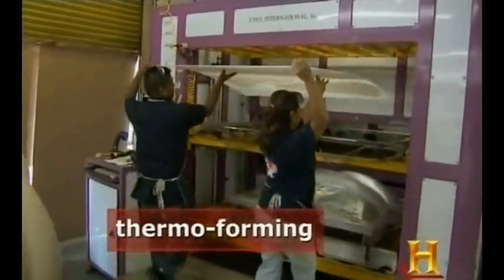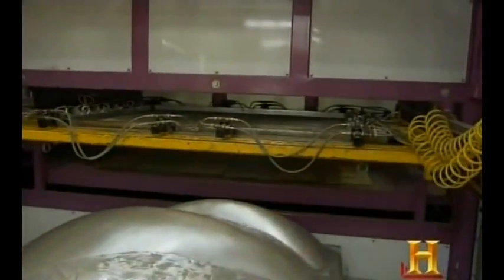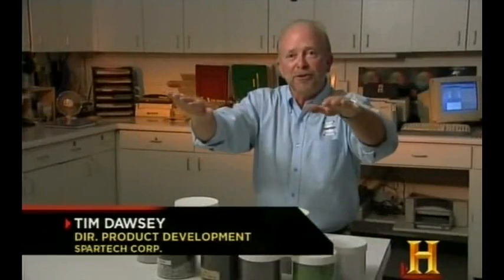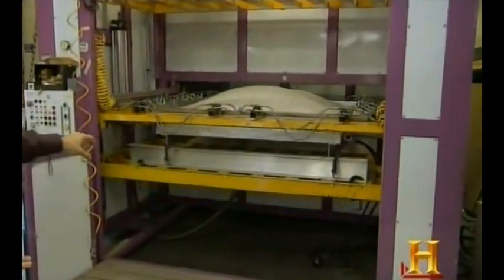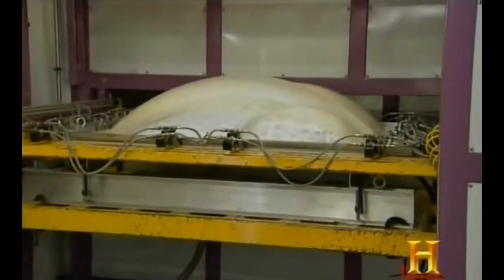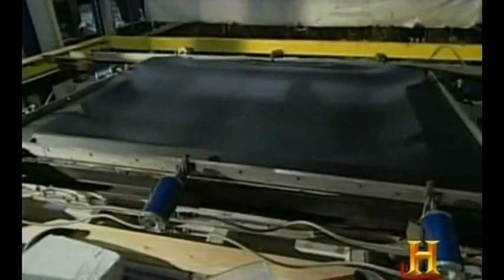You put the sheet in a couple of ovens and gently heat it — as opposed to the vigorous heating used to melt it — and it will begin to soften until it begins to sag. That sag is what they look for; the sheet is then moved and put over a mold, and the vacuum forming technique pulls it down and sucks it down to make the form of whatever part it is that you want. Thermoforming is a key method for custom plastic manufacturing, but there are others, including welding.